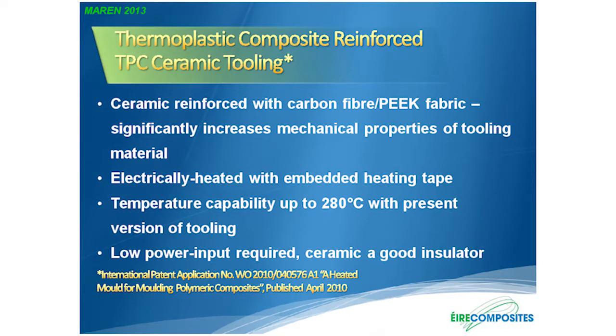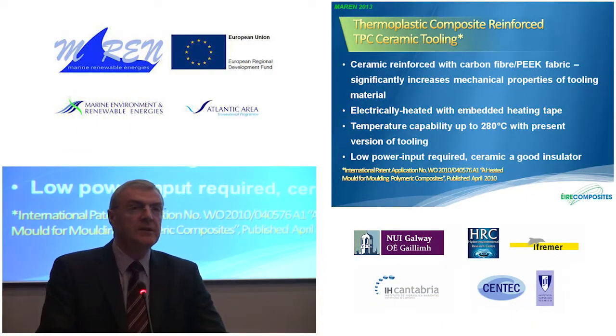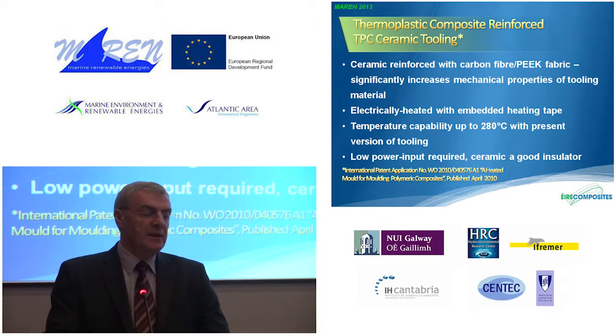And so the technology that we produced, having worked with these, is what we now refer to as thermoplastic composite reinforced ceramics, or TPC ceramic tooling. The technology consists of 3 elements: ceramic matrix, which is reinforced with carbon fibre and PEEK fabric. The combination of these 3 materials gives you significantly increased mechanical properties in the tooling, which is perfect for producing